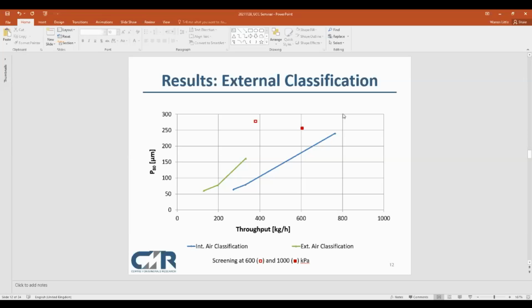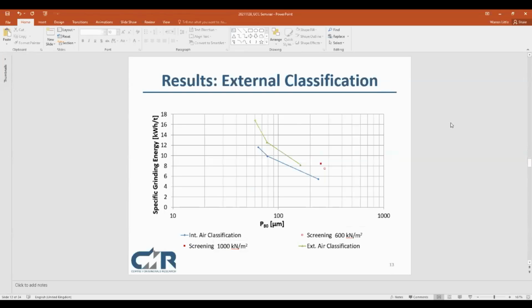Looking at the throughput of the two circuits, we see the external air classification circuit having lower throughput than the internal air classifier. And for the screening, as is expected, the 600 kilonewton has a lower throughput than the 1000 kilonewton. How this translates into specific grinding energy: the external air classification specific grinding energy, the green line, is higher than that obtained for the internal air classifier. The two circuits have similar power requirements, but the lower throughput for the external air classifier shows up as a higher specific grinding energy.